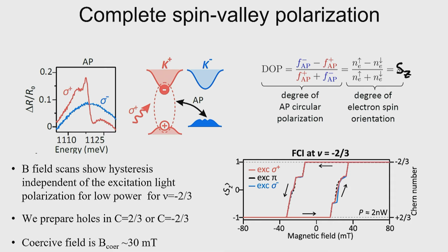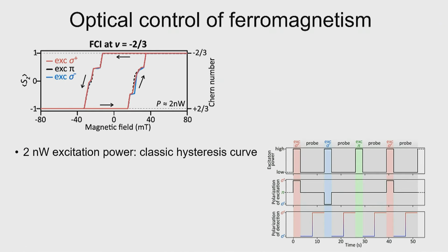Okay, so even at 0 Tesla, you have a finite magnetization, and that magnetization depends on where you are coming from, whether you come from a higher magnetic field or positive magnetic field or negative magnetic field. And this we check at low powers optically, and we see the same hysteresis curve for any polarization that you can choose. Okay, so in this case, this was done at 2/3, so the Chern number also changes from 2/3 to minus 2/3 to 2/3, etc., with magnetic field. That by itself was known before.